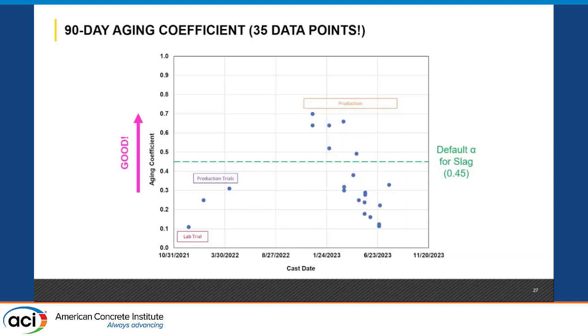And then when we moved to production, things got funny. But the literature will tell you slag should be around this line, and instead it was just like that. I mean, this is just noise in the data. A big topic that's happening in the service life committee is what's the difference between your design service life and your as-built service life. And this would tell you abysmal, because every time you drop below 0.3, you're probably failing your service life.